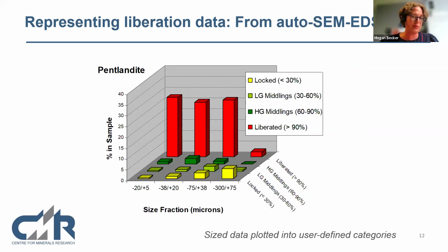Another way that's quite popular is to group it a bit further using terminology like locked, middlings and liberated. And again, it's done on a size-by-size basis. In this way, you see most of the locked material sits in the plus 75 micron. Most of the liberated material sits sub 75 microns.